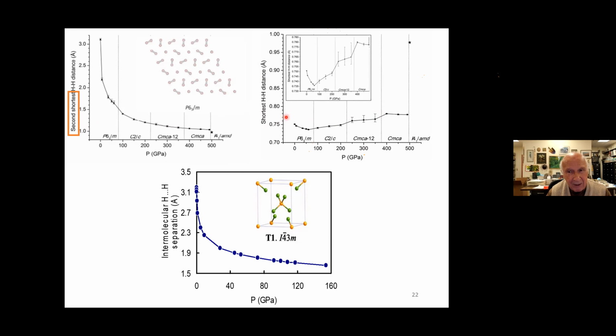Not the trivial games that are being played by the bonded distance, so to speak, but you've squeezed out the space between molecules, but the molecules remain. This is illustrated below. This is silane, a calculation on silane over a range of pressures in a structure which has 2 molecules of SiH4 in a unit cell. And this is the distance between one green ball and the green ball in the next molecule. And that one you also see goes down in the first 10 gigapascals by 1 angstrom. The molecules are pushed closer together. I can't show you any clearer than that how this happens.